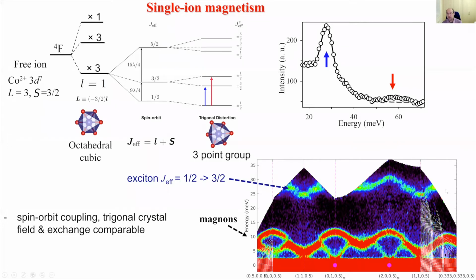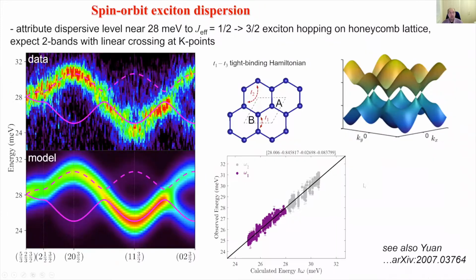So this is the magnon dispersion, and here is the transition of the crystal field level or exciton at higher energies. And we can again analyze that and compare it with what we expect theoretically for excitons now hopping between the two sites of a honeycomb lattice. So the exciton is a local transition to an excited spin orbital state, and then through exchange, we expect that that can hop also onto sites of the lattice. And that's equivalent to, again, the problem of hopping on the honeycomb lattice as in graphene, but with an energy offset. So again, we expect two bands that touch at the corners of the Brillouin zone.